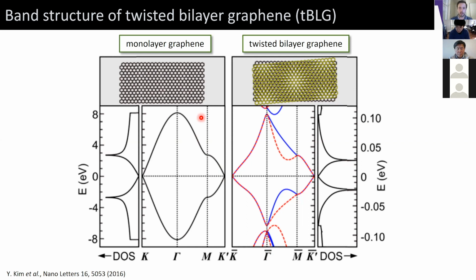For a twisted bilayer graphene at small twist angle, the band structure looks very similar to monolayer graphene, but now the energy scales are substantially smaller. So whereas in monolayer graphene, we're considering bands on the scale of electron volts, now the low energy bands of twisted bilayer graphene are on the scale of tens of milli-electron volts. And in some very simple hand-waving way, you can think that this Moiré pattern is effectively acting like a much larger unit cell for the graphene. And so we recalculate the band structure and everything looks roughly similar, but now all of the energy scales are smaller because this lattice constant is much larger.